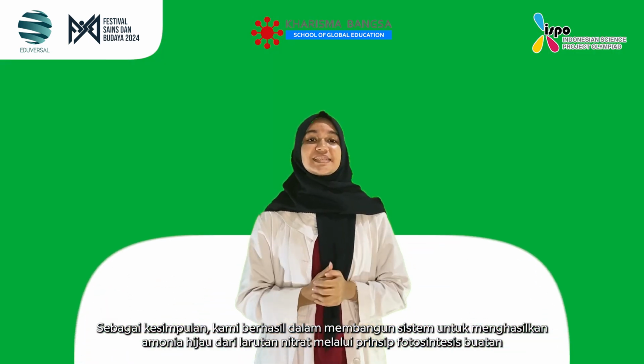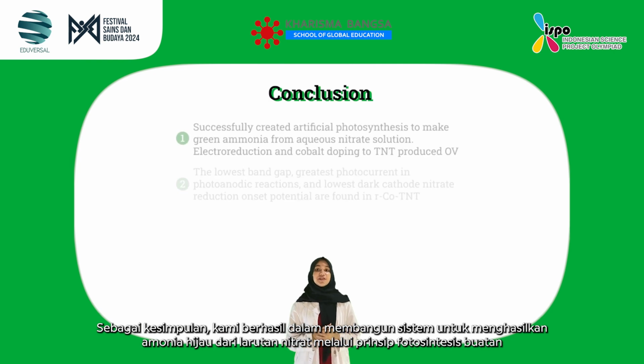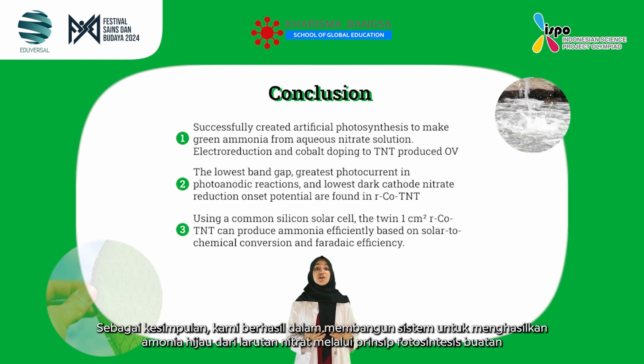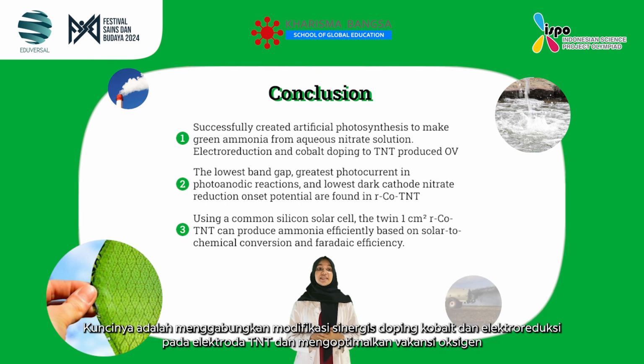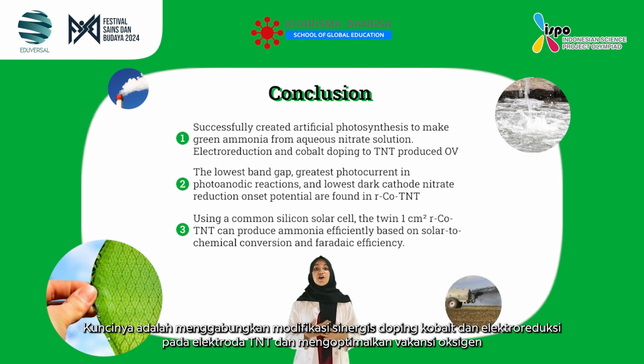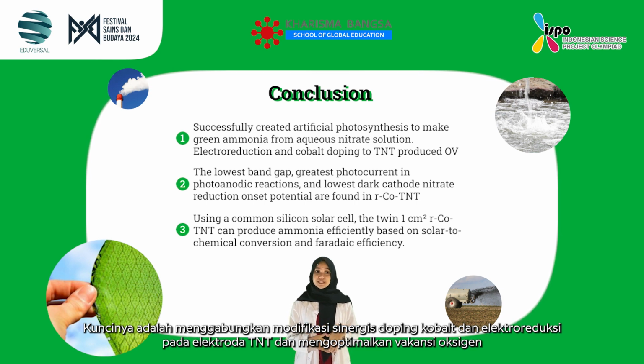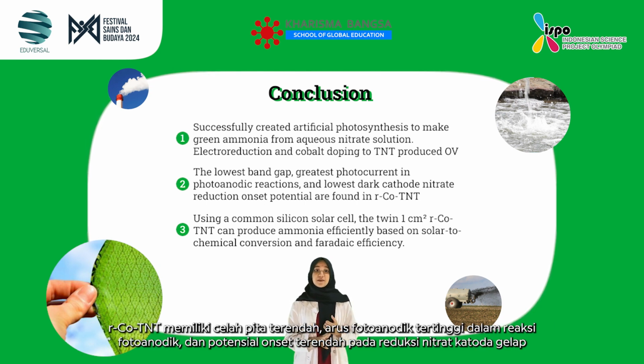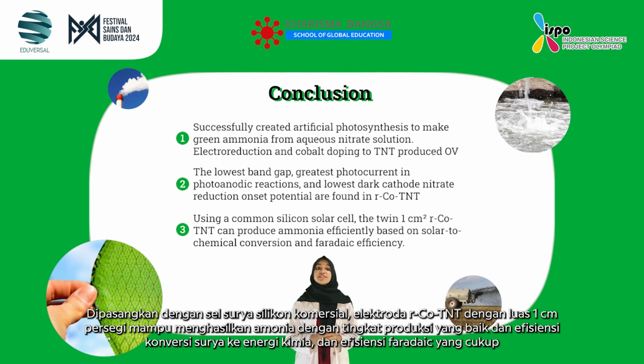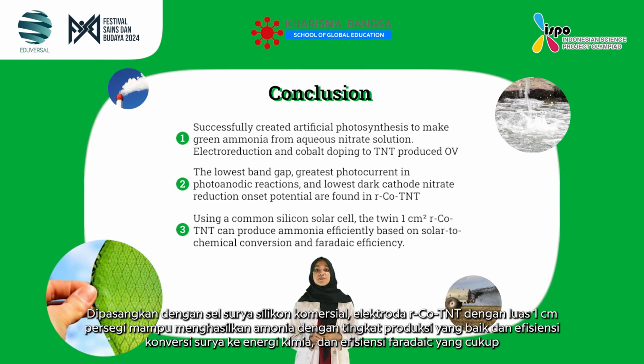In conclusion, we've been successful in constructing the system to generate green ammonia from aqueous nitrate solution through artificial photosynthesis principle. The key was to incorporate synergistic modifiers of cobalt doping and electroreduction to TNT electrodes which optimize oxygen vacancy. The RCo-TNT has the lowest band gap, highest photocurrent in photoanodic reaction, and the lowest onset potential at dark cathode nitrate reduction. Coupled by a commercial silicon solar cell, the twin 1 cm square RCo-TNT could generate ammonia with a fine production rate, solar to chemical conversion efficiency, and faradaic efficiency.